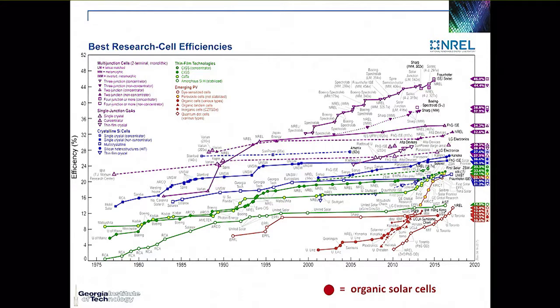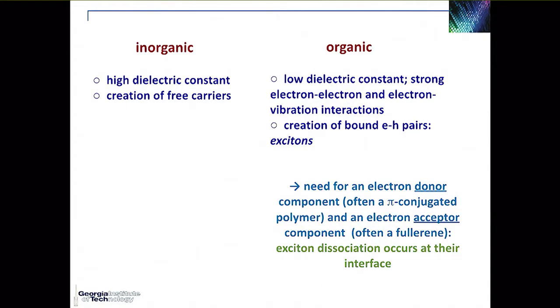But if you look at perovskites, as well as silicon or other types of inorganic cells, the photophysics is really different from the one that you have in organic solar cells. Indeed, in silicon or perovskites, you have a very high dielectric constant, at least in the case of the 3D perovskites, so that as a photon is absorbed in silicon or those 3D perovskites, the hole and the electron can very freely move apart from one another, so you have an immediate creation of free carriers.